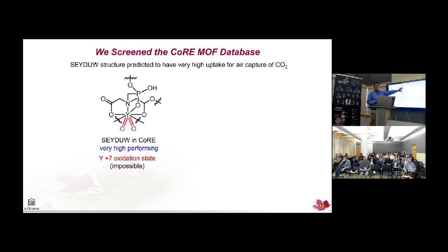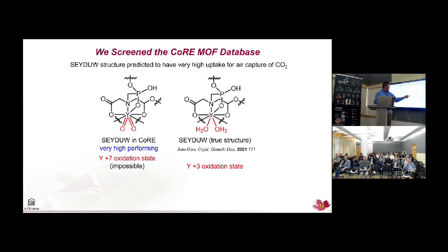So back to this, obviously there's clearly a problem with this structure that's supposed to be clean. We went to the original paper and found that the oxygens were not part of oxo ligands, but were part of aqua ligands. If you do your electron counting there with the aqua ligands, then yttrium is in its familiar +3 oxidation state. So they had not put the protons back properly when they created that database. It's normal not to have the protons in the CSD structure because the experiment doesn't pick up on it. Importantly, we then redid the calculations. It was pretty low performing.